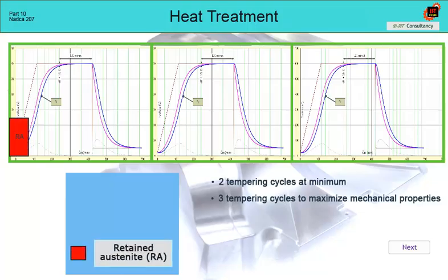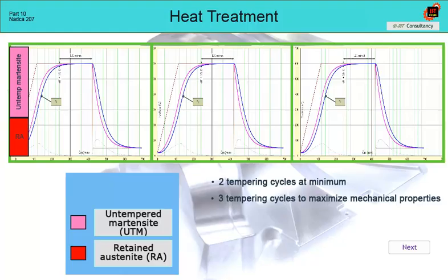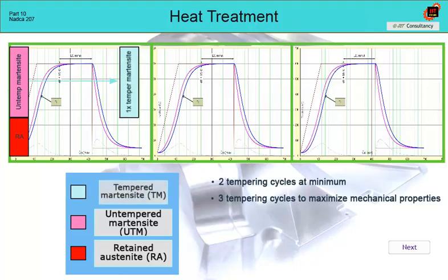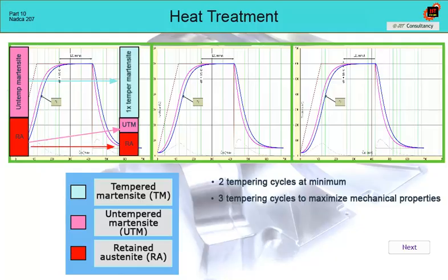After quenching, there may be more than 50% of residual austenite in the core of the insert, thus austenite where the transformation to martensite has not yet taken place. The remaining part is untempered martensite. After the first tempering, only the martensite formed during the quenching process is tempered. At the same time, with the continued transformation of residual austenite, new, not yet tempered martensite is formed. The structure would therefore consist of once tempered martensite, untempered martensite, and residual austenite.